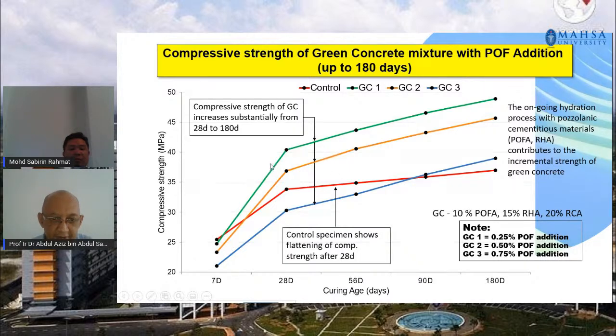As you can see, the strength is not only better than the green concrete with 0 fiber, but it also shows an increment up to 180 days. It is not showing any dropping in strength. It is showing an increment. The same goes for the other mix as well. Both are showing an increment as compared to the 0% of fiber. This shows that the concrete strength is increasing as the days go by. It has gone more than 28 days, and the strength is still increasing.